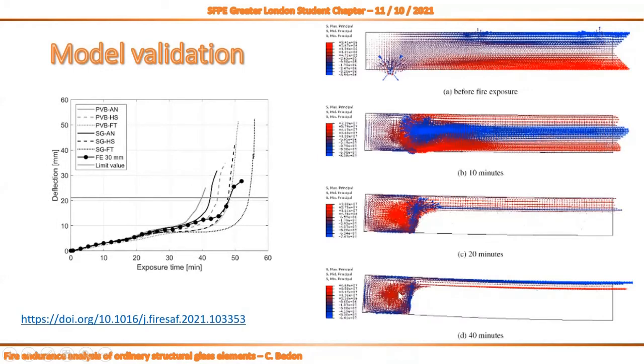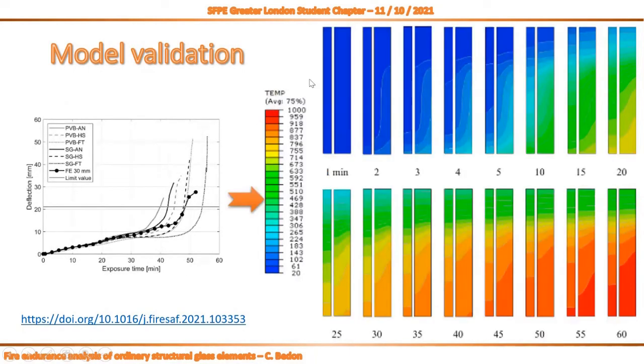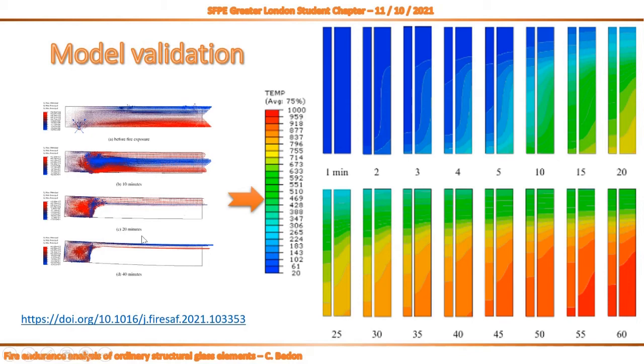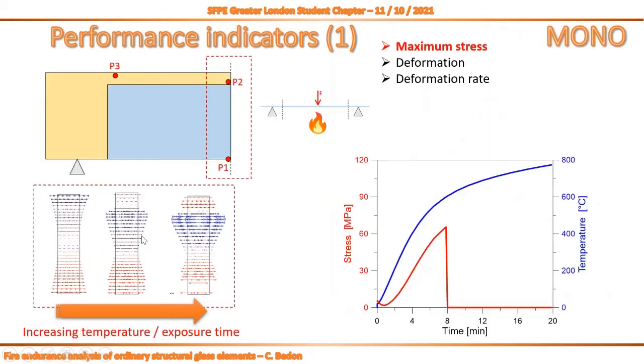The problem is even more complex because if we look at the temperature evolution and distribution through the thickness of our resisting section, you can see something like this from 1 minute of exposure up to 60 minutes. Temperature, for sure, is not uniform in the height of the section, but also in the thickness. And so this is the reason of, let's say, unsymmetrical and non-uniform stress peaks in glass. And you can see again the detail.